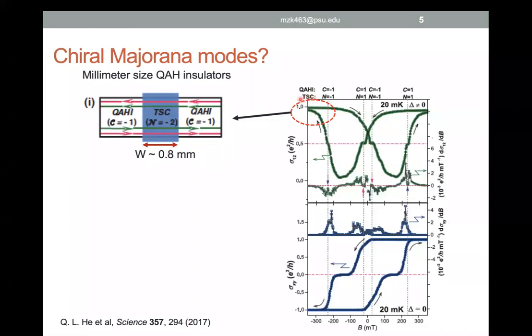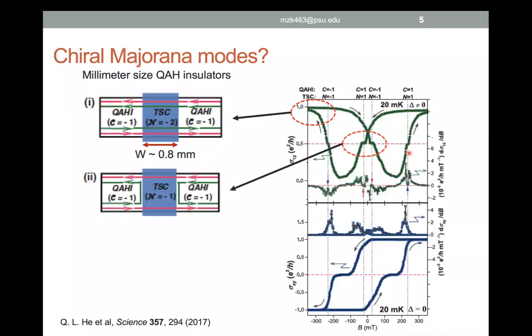They saw that if you are in a well magnetized region where the magnetization is either up or down, then consistent with the theory you have two chiral Majorana edge modes, but the effective result is that you will observe a quantized value of the conductance if you look at the two terminal conductance measured across this superconducting strip. Interestingly, however, they observed that during the magnetization reversal, you can see a half quantized conductance. They interpreted this half quantized conductance as the evidence for the chiral Majorana mode.